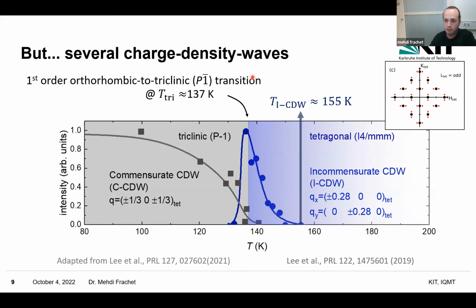So, no long-range magnetic order, but what makes this compound even more interesting is the discovery of several charge density waves a few years ago by the group of Peter Abbamonte. What they discovered is that upon cooling in this tetragonal phase, an incommensurate charge density wave first develops. It is strongly enhanced below a given temperature of 155, 160 Kelvin. This incommensurate wave has two modulations along the x and y axes, with the same modulation along the two axes. It is enhanced and then suppressed when you go into the triclinic phase. And there is another charge density wave that develops at the expense of this one, which is commensurate and uniaxial.